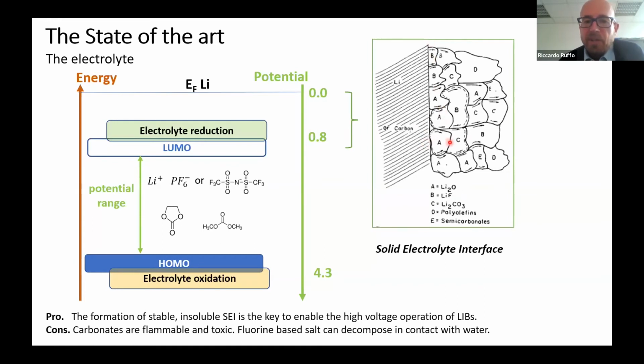And this is not just a passivation layer, it's a layer which avoids further contact between the electrolyte and the lithiated graphite, which would reduce the electrolyte, but at the same time, it guarantees also the transport of ions. So this is the reason why we call it solid electrolyte interface. And it increases the operative voltage of our batteries. We usually use carbonates, which are flammable and toxic, and also fluorine-based salts, which can decompose in contact with water, giving HF. So there are a lot of improvements that we can try inside the electrolyte.